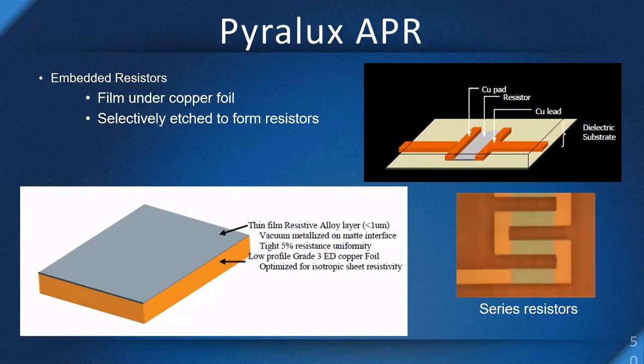Just a note that there is something called Pyralux APR. It's not an inexpensive material, but it's a technology that exists. Again, we'll probably see more use as circuits become more complicated. Basically, it's a nichrome layer that's deposited on the backside of the copper foil. And the foil is laminated down to the polyimide dielectric, with the nichrome layer touching the dielectric. And then you can selectively etch. So you etch your copper, you come back and you etch away the nichrome, and then you come back and etch away copper to reveal the nichrome, where you only have that bridging your copper circuitry, and that becomes your resistor. Interesting technology. It's used in rigid as well as flex, but it's just a quick introduction into this technology. APR is available.